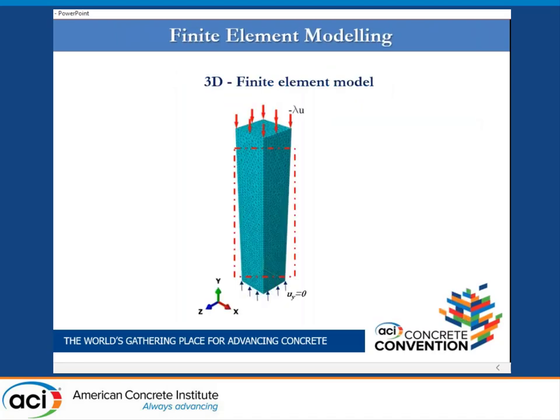All tests were modeled in three dimensions to replicate the column entirely. The load was applied at the top of the columns, while at the bottom the columns were clamped. The mesh was based on the geometry with linear interpolation functions via 3D solid elements (C3D4). The external reinforcement was modelled by a macro-model approach, without distinguishing between the external reinforcement and the concrete substrate. The tests were conducted under displacement control.